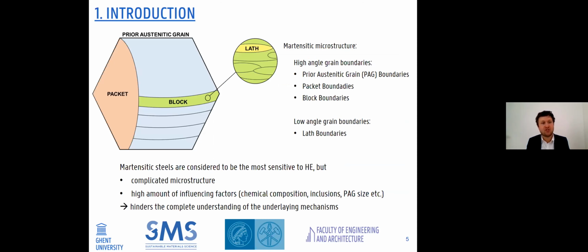As a second part in the introduction, I want to focus on the microstructure, because here we deal indeed with the martensitic microstructure. And as we know, these martensitic steel grades come with high strengths, but they're also quite prone to hydrogen embrittlement. Why? Because it's a quite complicated microstructure containing both high angle and low angle grain boundaries. As high angle grain boundaries, we have the prior austenitic grain boundaries, but also packet and block boundaries are present in the microstructure as shown in the figure. We also have low angle grain boundaries like the lath boundaries that resemble more dislocations.